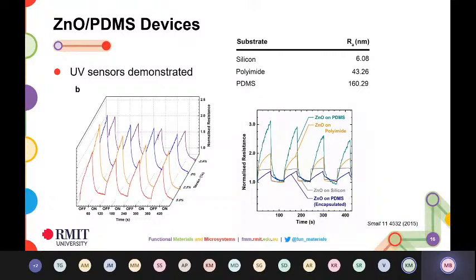The other thing which is fascinating with these materials is the more you micro or nano pattern them, the more strain you can apply on them. With the zinc oxide work, these are quite large area devices. So you have a thin film sitting everywhere, which means you can't really go beyond, say, 5 or 6%. If you micro pattern it, you can go up to around 15%. If you nano pattern it, you can go up to around 25% of strain. But that's a really interesting question in terms of whether the strain is impacting the band gap of the material.